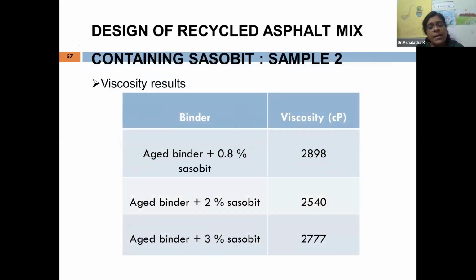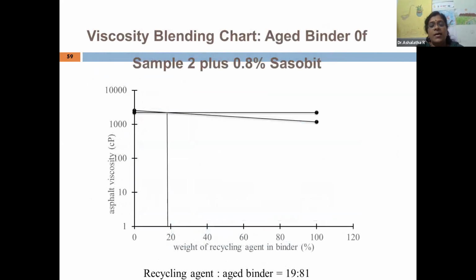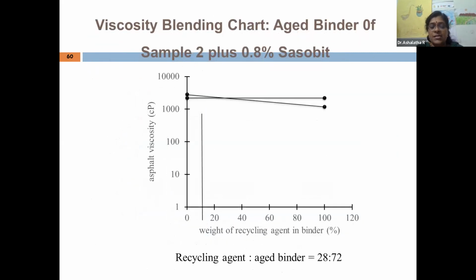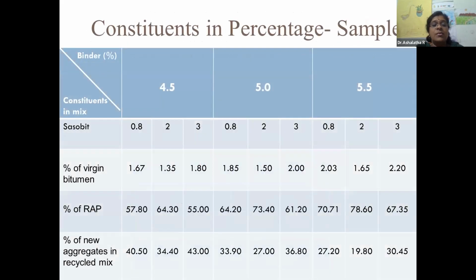And then we repeated the same exercise on sample 2 by varying the Sasobit percentage. We found out the ratio of the recycling agent and aged binder, and also for different percentages of Sasobit, keeping the binder constant, the percentage of virgin bitumen, percentage of the RAP, and percentage of new aggregate in the recycled mix. So this was done for 4.5%, 5, and 5.5% binder with 3 different combinations of Sasobit.